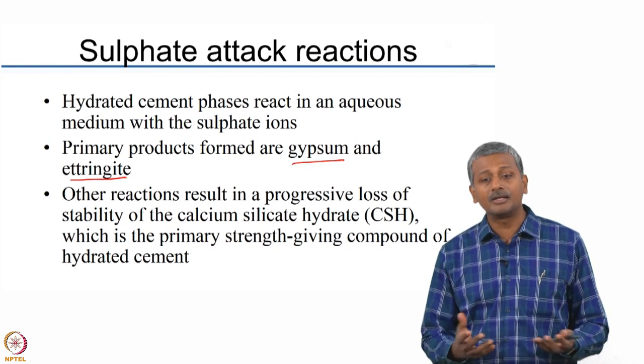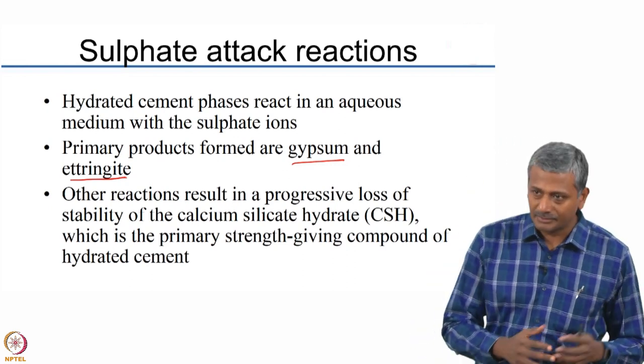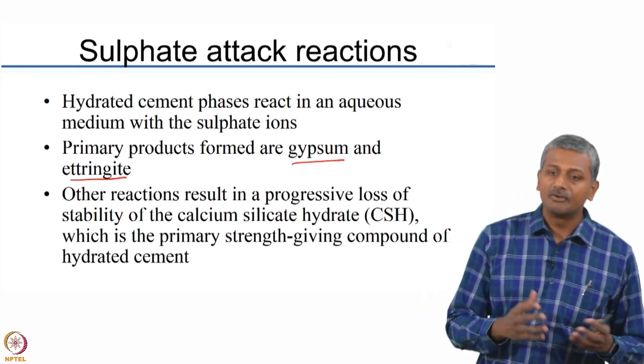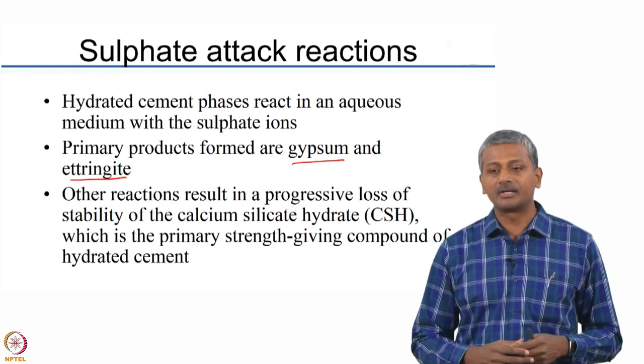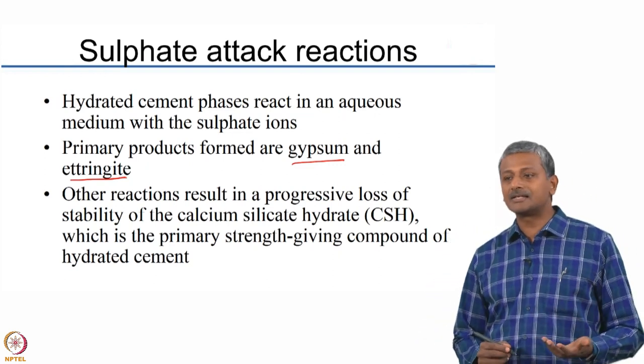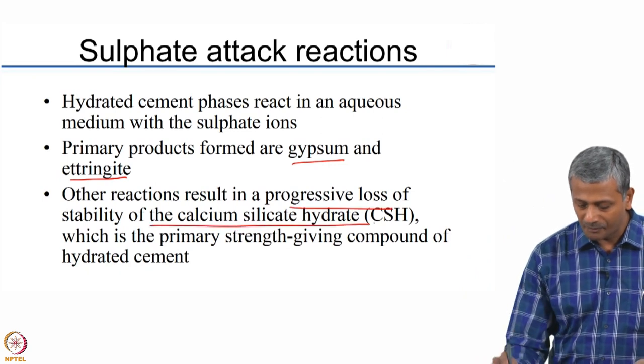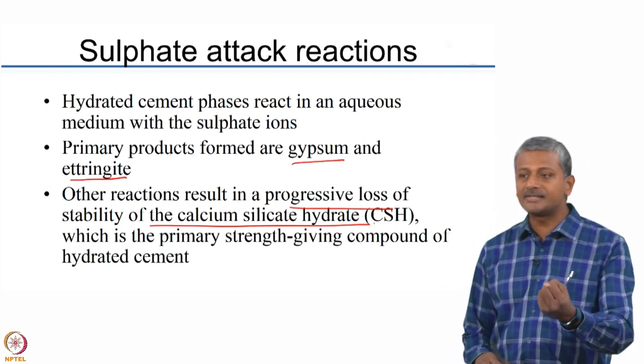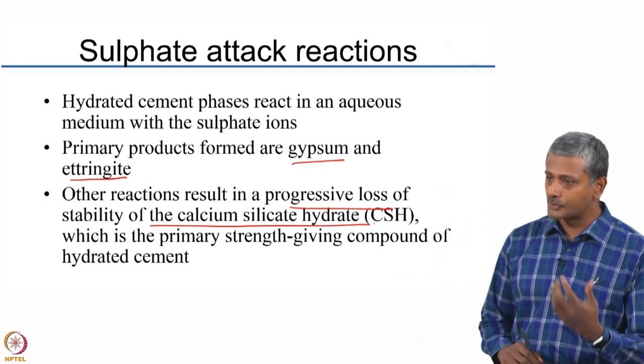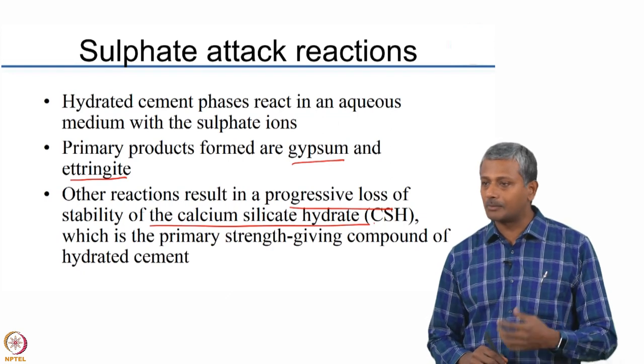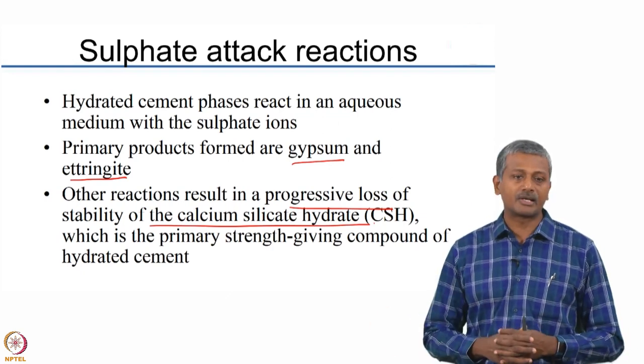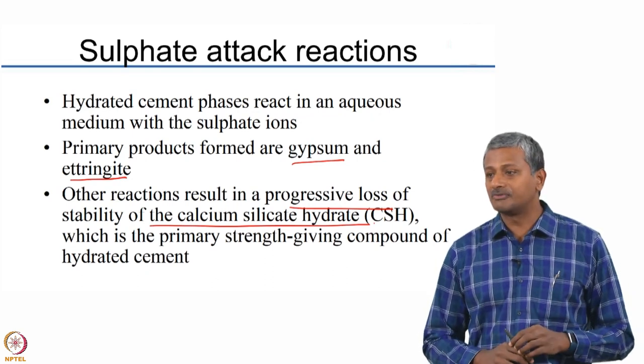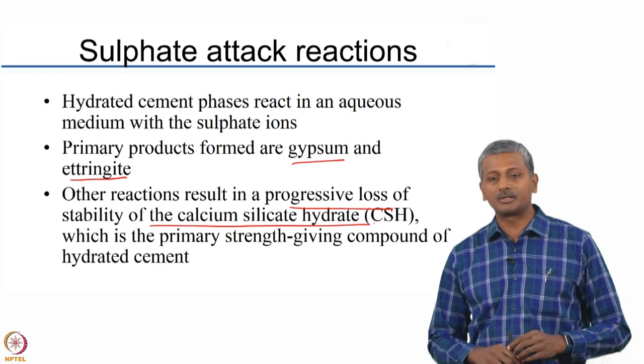This formation of ettringite is now happening in a hardened concrete. Ettringite has an expansive nature, so if it forms in hardened concrete, the associated expansion can lead to cracking. Beyond this, there is a much more deleterious reaction which is a progressive loss of stability of CSH — the adhesive phase inside cement paste that primarily binds aggregate together. Progressive loss of CSH structure can lead to a major deterioration in the characteristics of the concrete. Other hydrate products like calcium hydroxide, ettringite, and monosulphate also fill porosity, enhancing structural characteristics, but the primary binding capacity is provided by CSH.